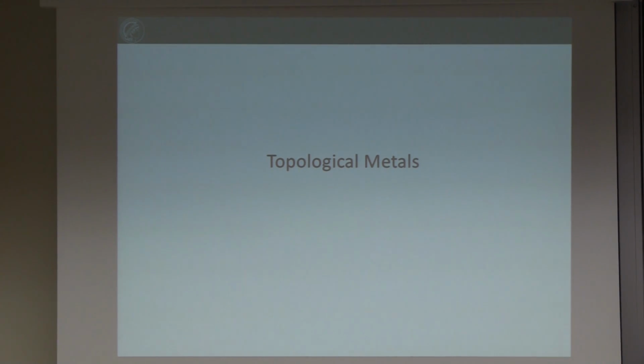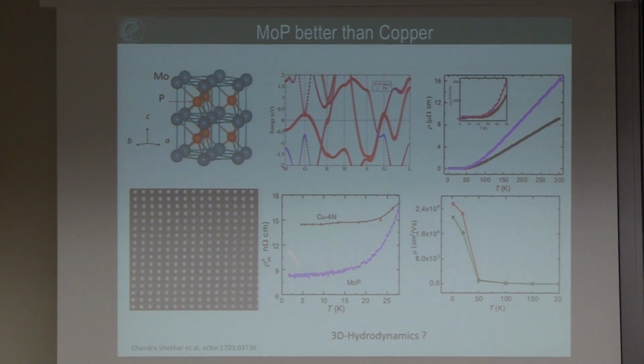Okay, I think I'm nearly done, but I think we can continue our work thinking about topological metals. We had a nice paper on gold, which is a topological metal, but also the whole story about hydrodynamics started with molybdenum phosphide, a triple point topological fermion system, which is more or less a metal. We see that the resistivity in this material is much lower than copper, and here again we found even in the metal a high mobility electron mobility.